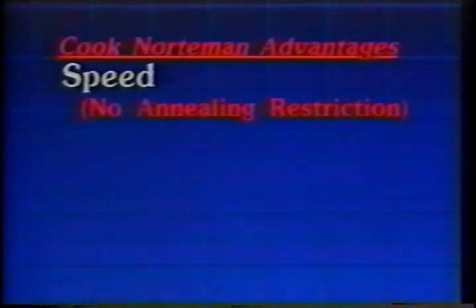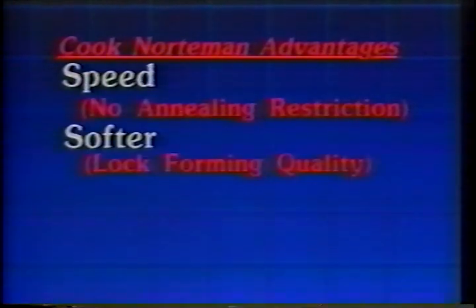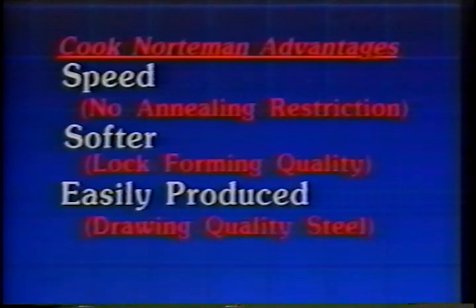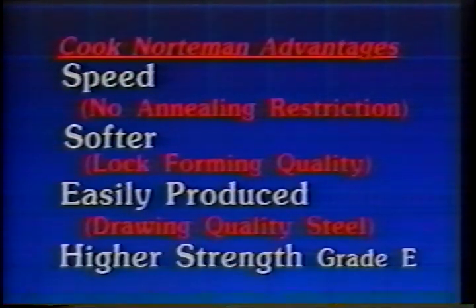The Cook Norteman advantages are speed because of no annealing restriction, softer lock-forming quality, easily produced drawing quality steel, and higher strength grade E. Why is the Cook Norteman softer than the Sendzimir? The Sendzimir continuous anneals in line, while the Cook Norteman uses more portable anneal previous to the line. The portable has the greater ability to make steel softer. Why is softer better? Because it's easier to form or draw. Remember our brand name, SofTite.